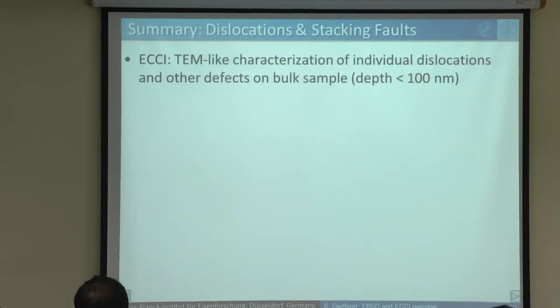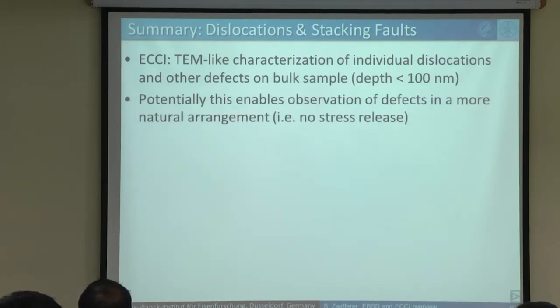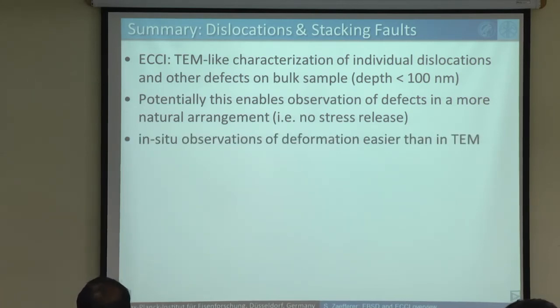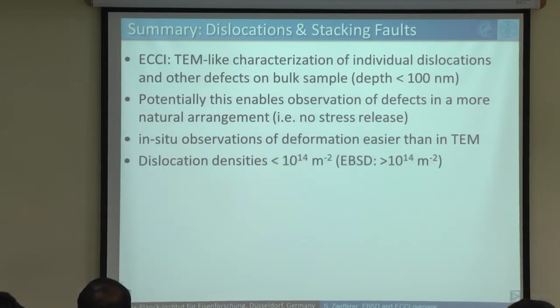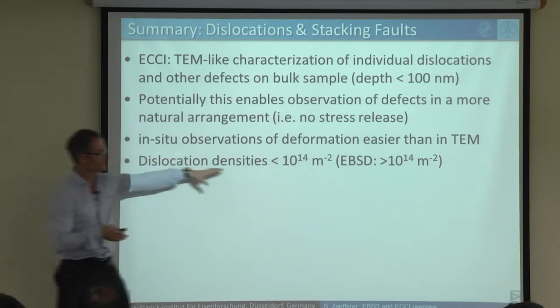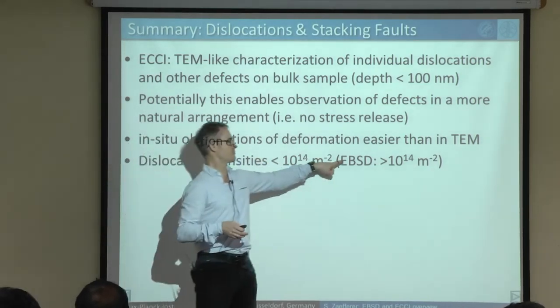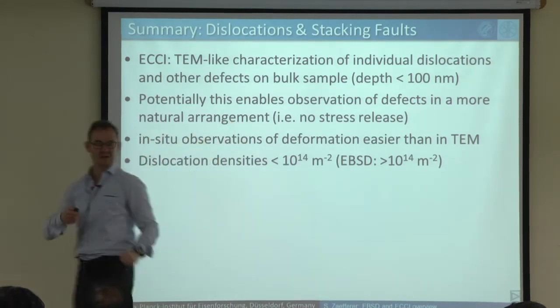Yes, and what can it do actually? So clear. You have seen it's giving TEM-like characterization of defects, of dislocations and stacking faults and nanotwins and even strain fields, but not on thin foils, but with bulk samples. This is a big advantage. And of course, this allows us to see things in a more natural arrangement. In a thin foil, when you make the thin foil, often the sample starts to release stresses, which you do not have in a bulk material. You can do very nice in situ experiments because you're keeping a bulk sample. You can look on dislocation densities up to the 10 to the 14, and for dislocation densities higher than that, you can use EBSD quite nicely.